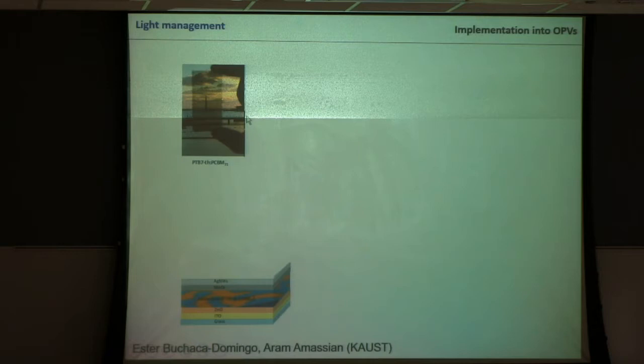So organic solar cells, very promising. As mentioned, we now get to 17%. However, they have an issue. We need to keep these active layers pretty thin to ensure that when we create charges in this active layer, they get to the electrode. This is a problem because while the organics absorb actually pretty much of the light, you never absorb all the sun that you put in, and you lose a lot because it's not absorbed by the active layer. So what can we do? We can put a mirror on top that reflects the light that was not absorbed.